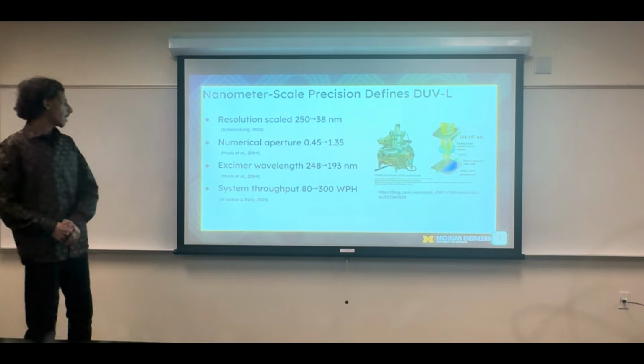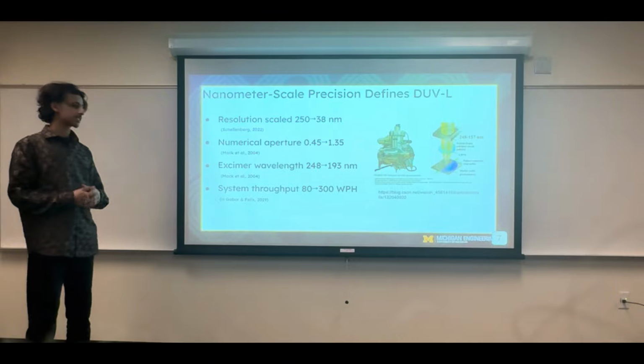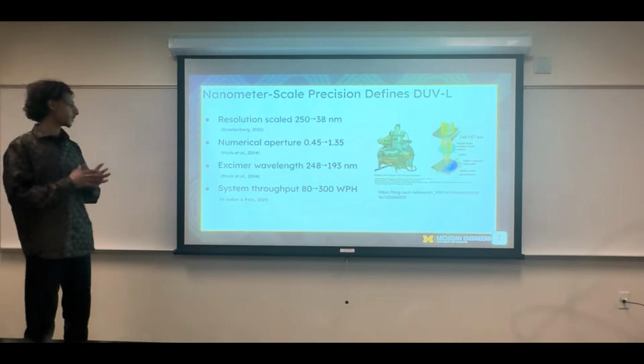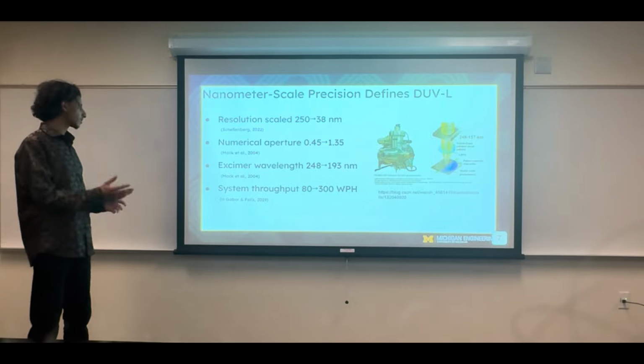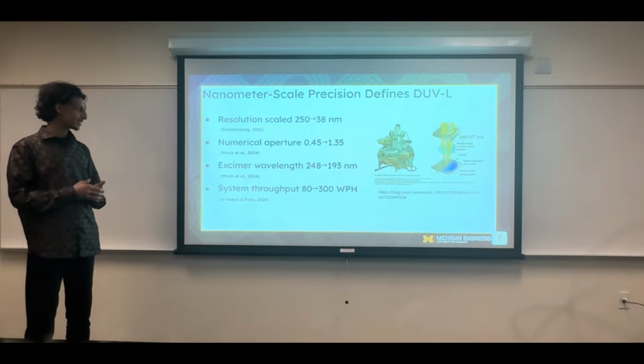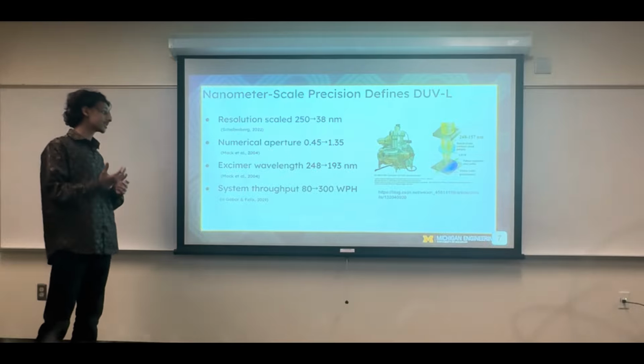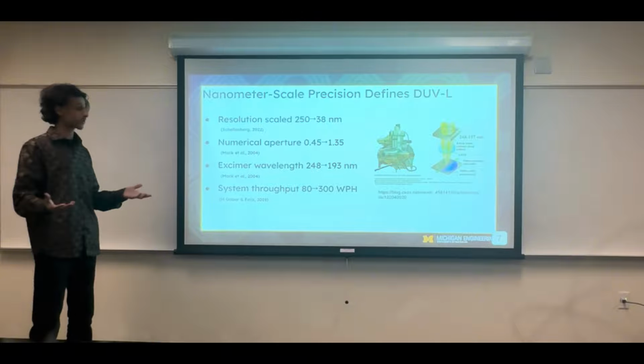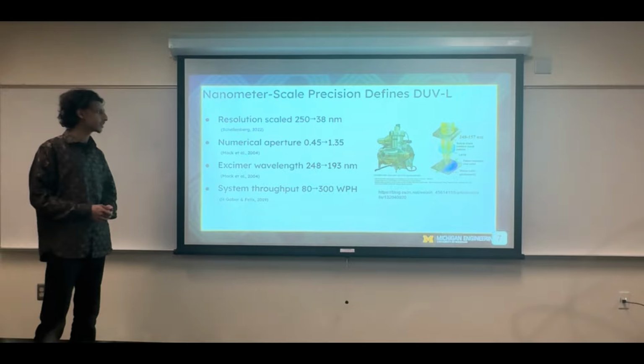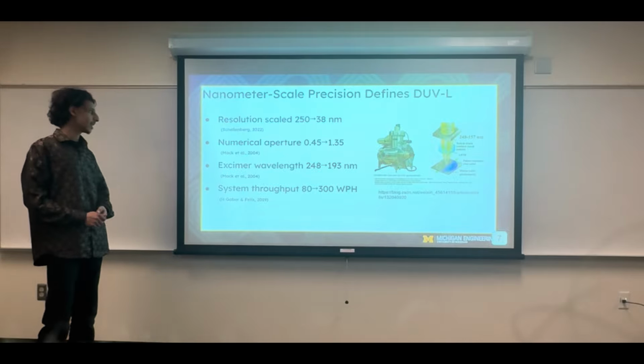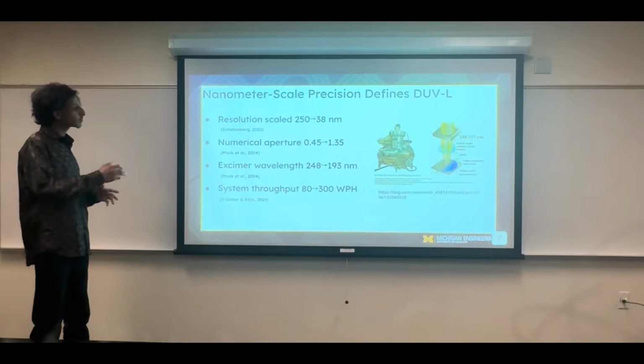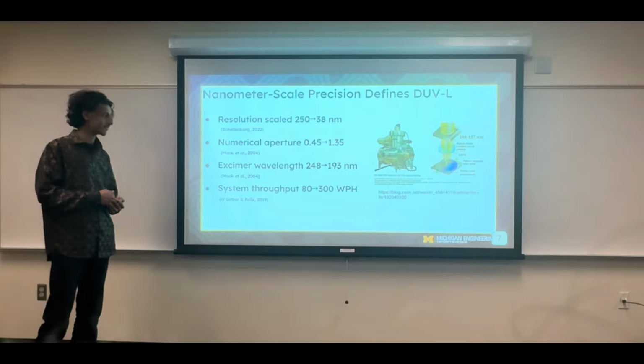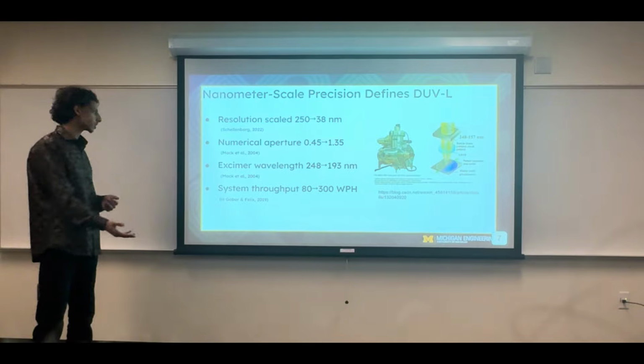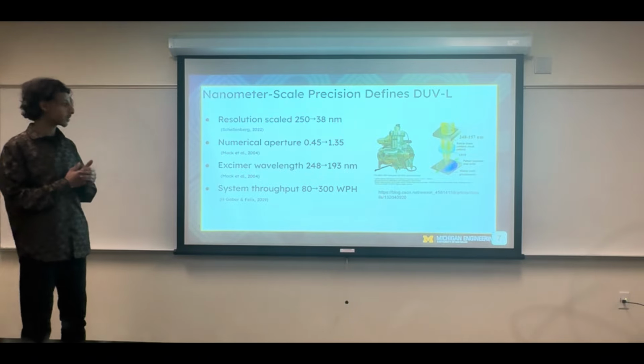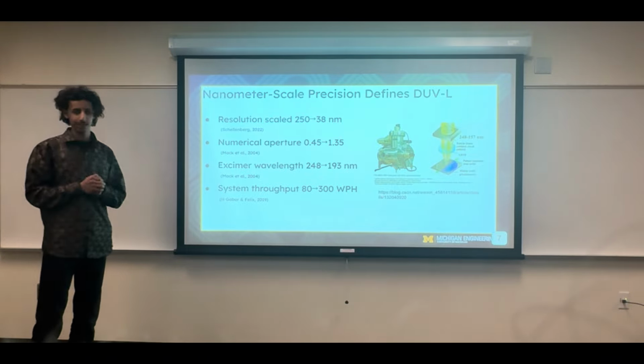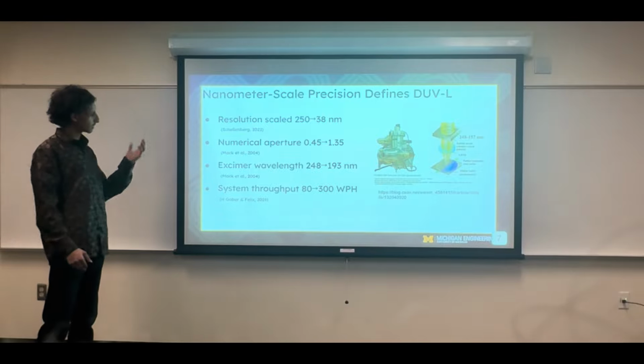Thank you, Kevin. The most important metric is resolution, which is essentially how small a feature size is able to be printed onto the wafer, and that is constrained by numerical aperture and the wavelength size. As the numerical aperture increases and the wavelength decreases, resolution also increases, and it has been scaled down from 250 nanometers to 38 nanometers. The numerical aperture also has been scaled, obviously, from 0.45 to 1.35, from dry to immersion, which utilizes ultra-pure water between the wafer and the lens itself, and that has increased the resolution, as mentioned before.